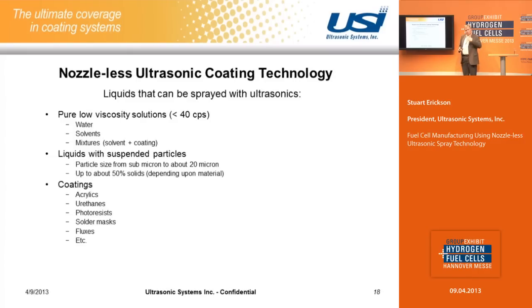Just general, with ultrasonics, the types of liquids that can be sprayed are low viscosity solutions. If you have a pure solution like water or solvent or some kind of a mixture of solvent and water, you can spray a low viscosity material of 40 centipoise or less. However, we can also spray materials that have suspended particles like fuel cell materials. These materials, the viscosity measures much higher than the 40 centipoise limit, but that's because of the way viscosity is measured, not the actual viscosity that the ultrasonic head sees.